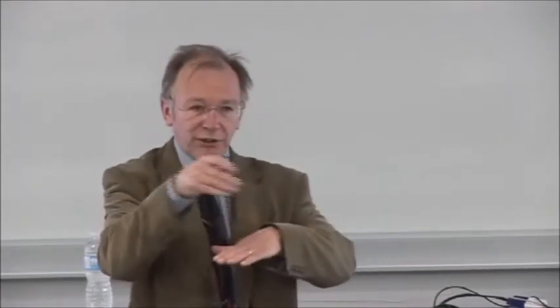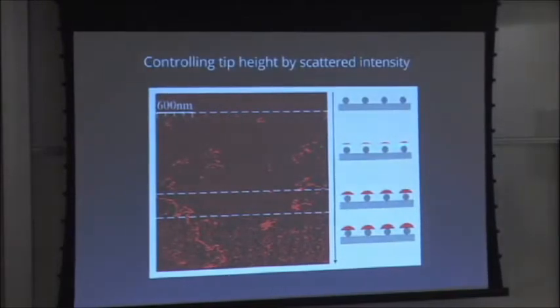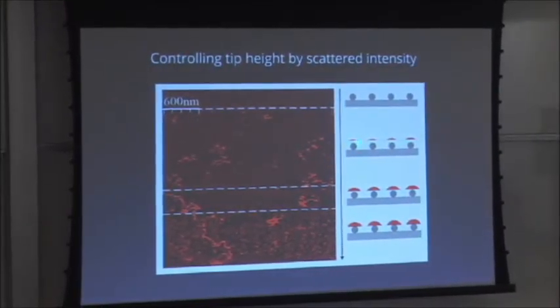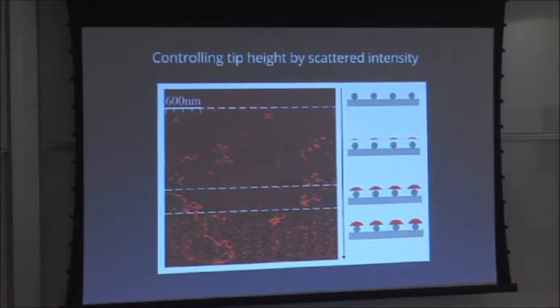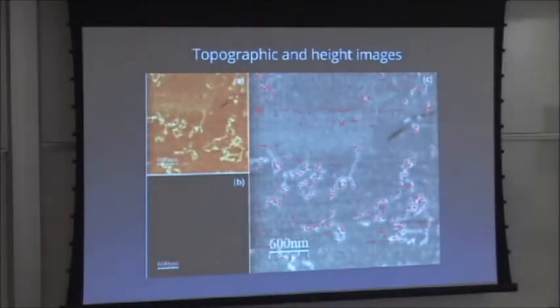And then we can measure the mechanical properties. We can measure the mechanical interaction between the probe and the sample. Scan really fast and just see what the coupling is to the sample. So this shows us approaching the surface. This is away, and then the red bit just shows where we are, just interacting with the tops of the DNA molecules. You can see the DNA molecules emerging from the background, and here you see a lot more background noise from the surface contamination. But here you're about right, just seeing the DNA molecules. We can do this really fast because there's really no feedback involved, which is the limiting factor. So now we have a high speed non-contact version. Okay.